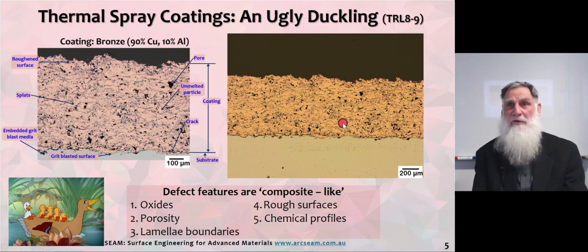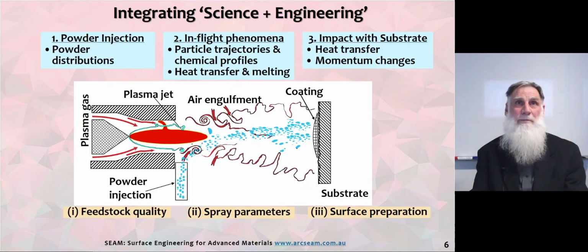And here's another example without all of the numbers and arrows on the actual micrograph. So the defect features of these coatings are composite-like. We have oxides, porosity, lamellar boundaries, rough surfaces, and chemical profiles. These coatings are really ugly when you look at them. But keep in mind that they're being used at technical readiness levels of 8 to 9. So although they may be considered as being quite strange or ugly, they do have beauty. And the beauty is contained within the defective features, which I'll describe in more detail.